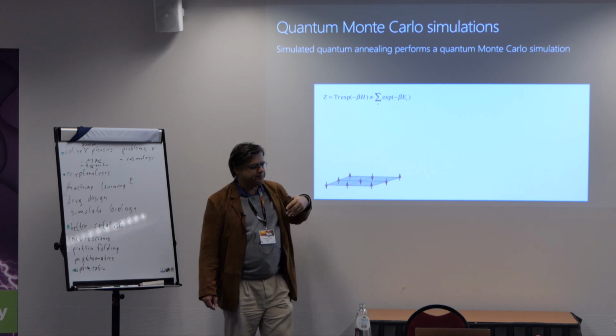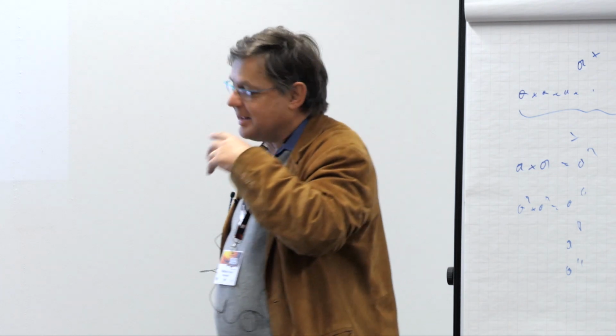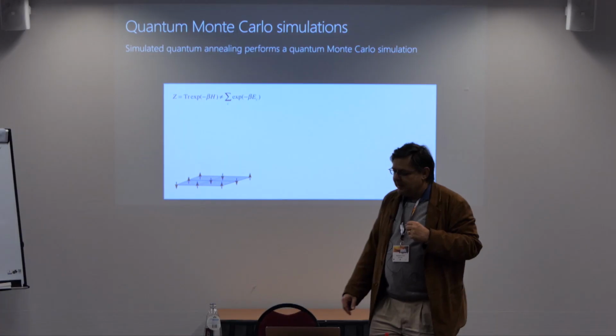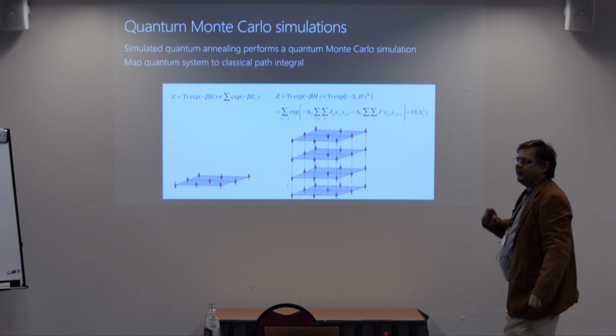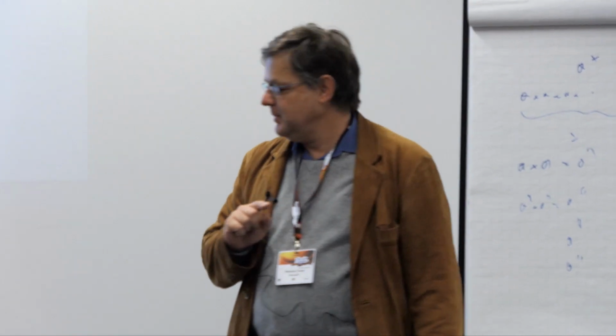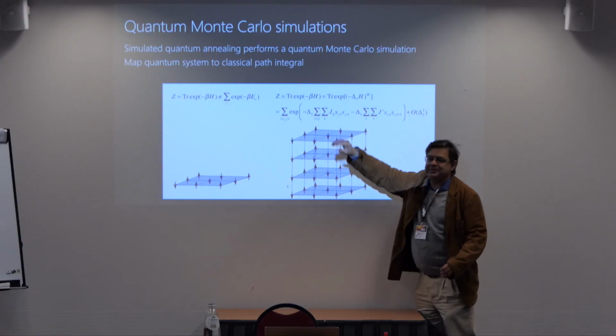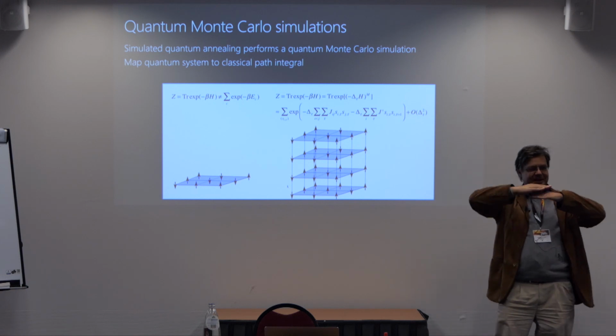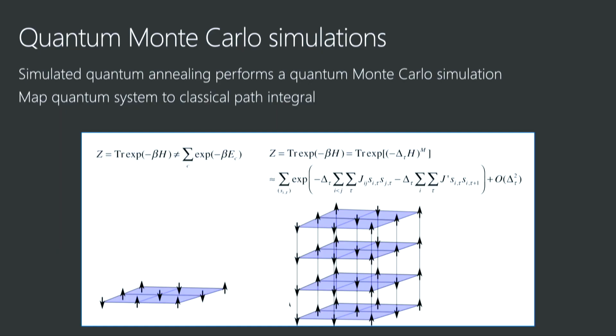And the partition function of the quantum system is the trace of the exponential of minus beta H. And that is hard to calculate. That is not like a classical partition function. But what one then does to simulate a quantum system, we actually map it first to a classical system. So we do a path integral representation where we represent the exponential of minus beta H as many small time steps in time, in imaginary time, and we do a path integral. And we always propagate by a small time step delta t. Then again, I get to my next quantum state.